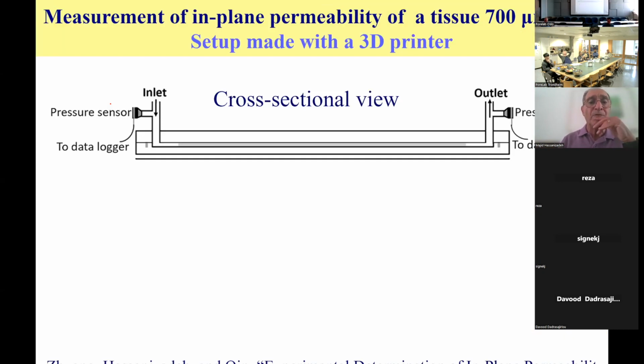For example, we wanted to measure the in-plane intrinsic permeability of a sheet. Now, you cannot just use a standard permeability measurement setup. For through-plane permeability, perpendicular is not much of a problem. You can use many layers. But for in-plane permeability, you cannot put more layers on top of each other, because then there is space between them. So we wanted to have one thin layer of a few hundred microns and a setup to measure that.